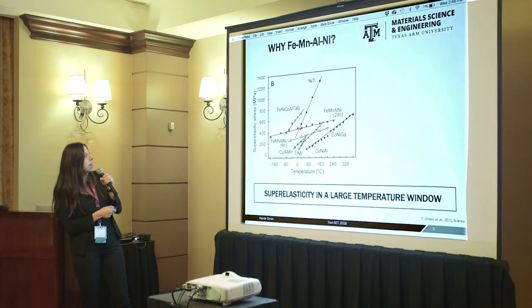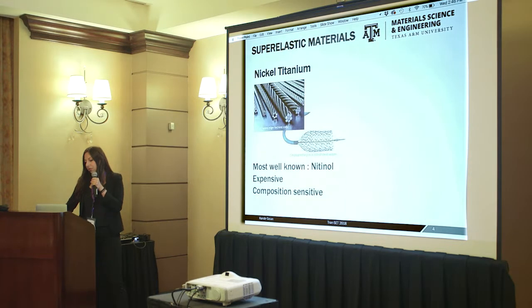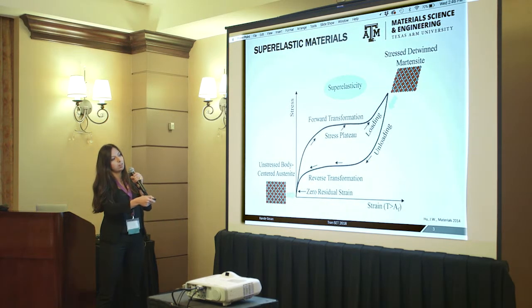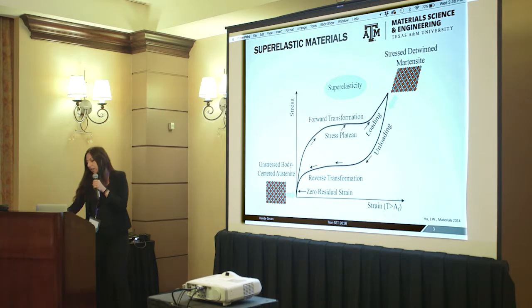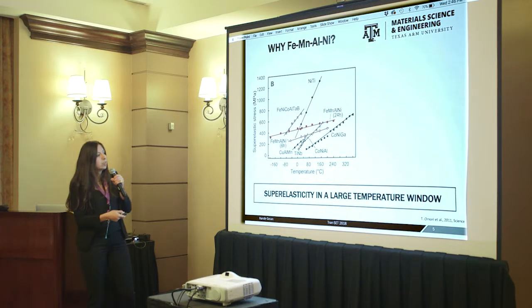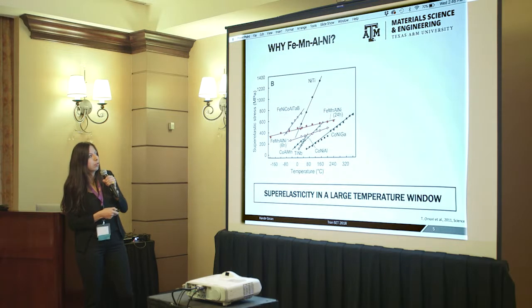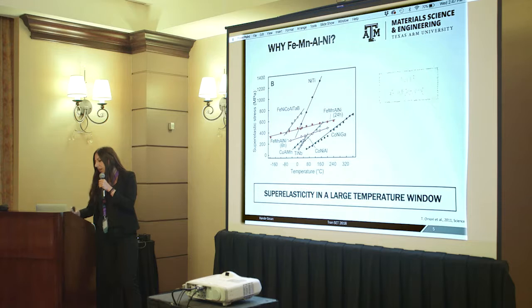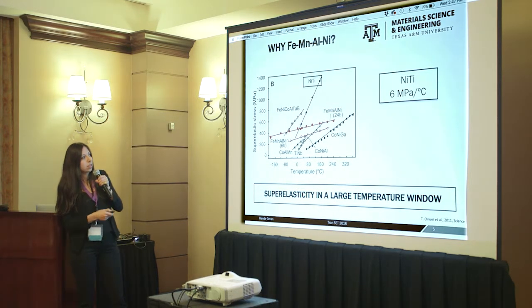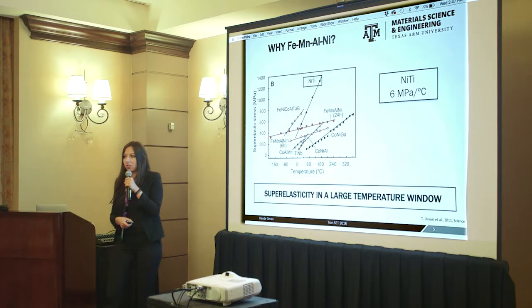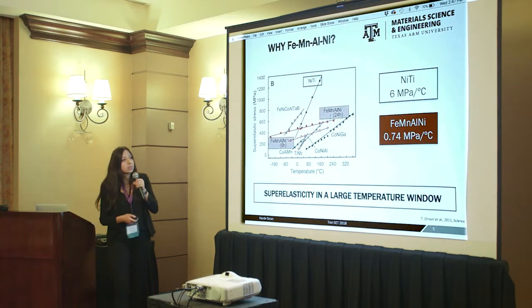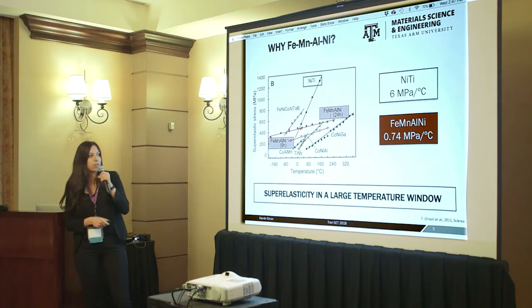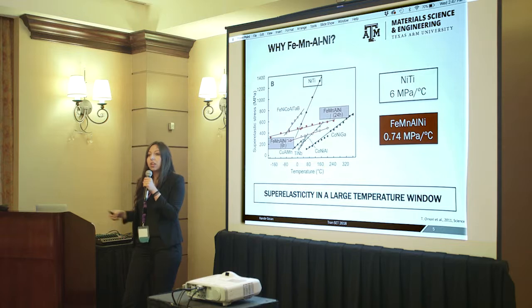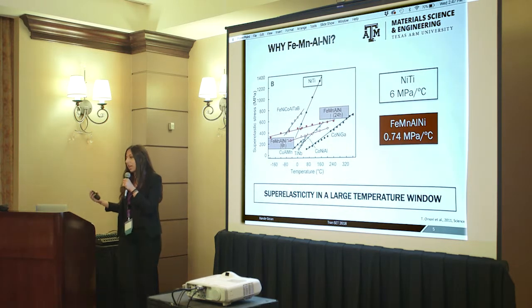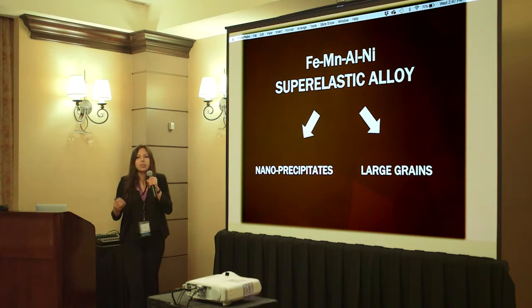For example, in this graph, this is the superelastic stress, which is a critical stress, where in the previous graph, around this stress you start to transform to martensite. This is what we call critical stress, versus temperature. The red line represents iron-based shape memory alloy and this line represents nickel titanium. As you can see, if we change 1 degree C, the critical stress of nickel titanium changes 6 megapascal. So this is a huge change. However, iron manganese aluminum nickel changes only 0.74 megapascal, which means that we can use this material without changing its properties over a wide temperature range. So in civil applications, you can use this in cold temperatures or in very hot temperatures, and you will still get the same response.